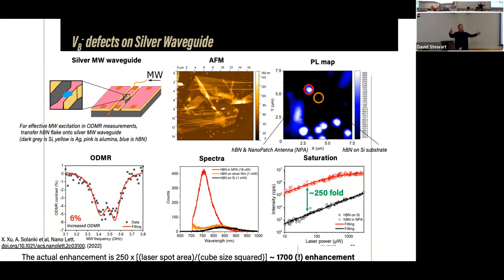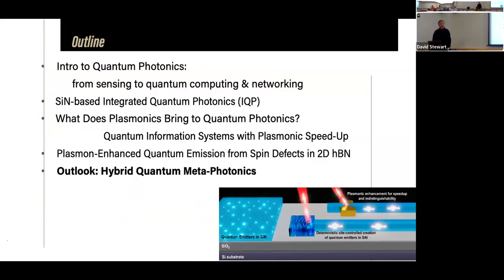But because the size of the laser beam is larger than the size of the cube, and the enhancement occurs only in the area of the cube, when we recalculate and take this into account, the actual enhancement is 1,700. Unfortunately, in this case it's not a single photon emitter because there are many of these defects, but the enhancement is good, and clearly this is also an opportunity to make good single photon emitters.